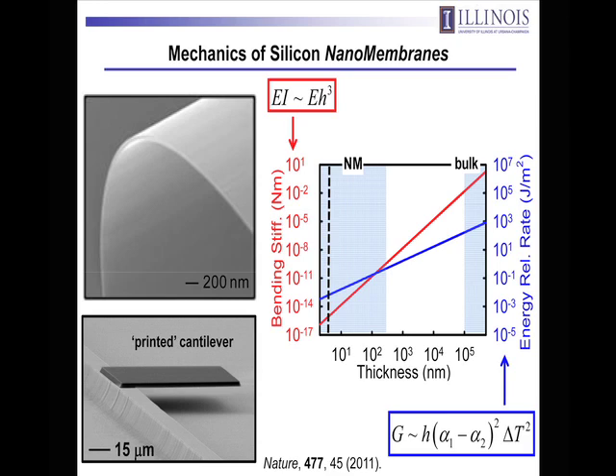You can keep it in that suspended state because in this very small geometry, surface forces can be dominating in terms of interface interactions. The other aspect that allows this to happen has to do with the propensity for cracks to form between that interface that forms due to van der Waals interactions.